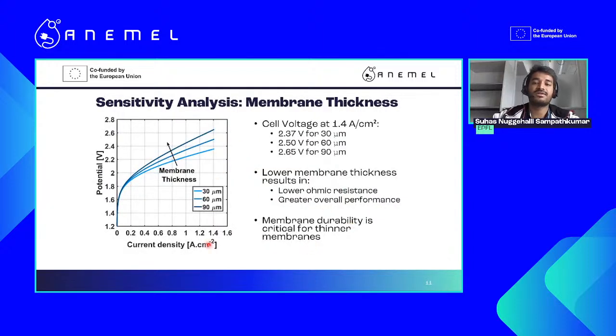So based on all this data, we also manually, or in the simulation, changed the membrane thickness by changing physically the thickness of the membrane, and then we saw that thinner membranes have better performance, thicker membranes have worse performance. And this was nice to know, because I think overall the effect of the membrane is also predominant compared to the pH. So this study was done in 1 molar KOH.